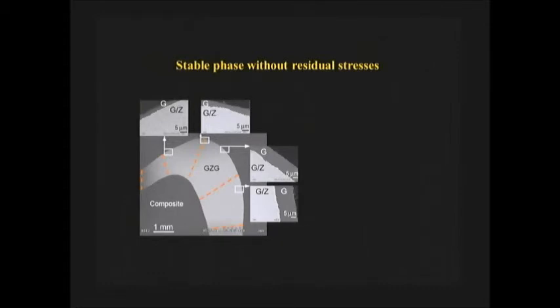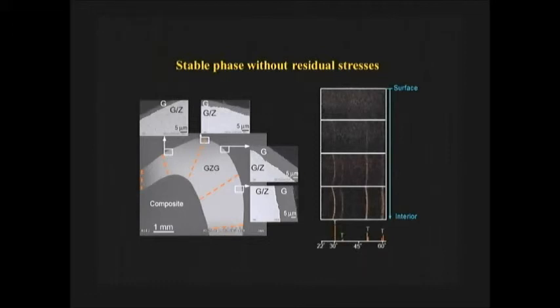One is to detect if we have monoclinic zirconia phase in this system. Two is to detect if we have any residual stresses in it. That's a more complex analysis, but X-ray is able to do this. What we showed is that from the surface glass, you see pretty much amorphous. There are no peaks there. That's a 2D detector here. By the time you get into the graded structure, you start to see some crystalline peaks. Then you go deeper, the peaks get darker, and in the interior very distinct zirconia peaks come up. If we compare to the powder X-ray diffraction files, indeed, they are tetragonal zirconia peaks. There are no monoclinic phases there.